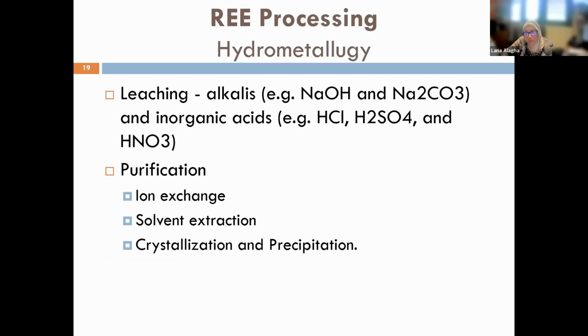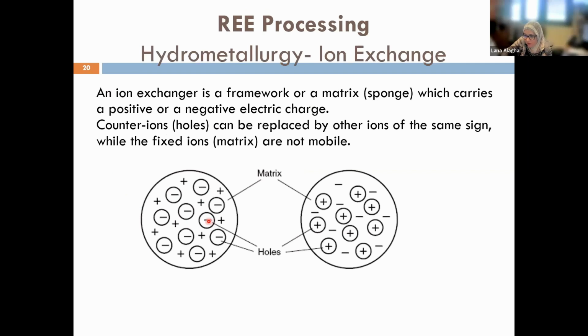Hydrometallurgy of rare earth, which is a chemical dissolution. We discussed physical separation to produce a concentrate that has mainly rare earth oxide. Now the hydrometallurgy part of the processing involves leaching and solution purification in order eventually to have pure rare earth compounds. So the agents for leaching involve alkalis like sodium hydroxide or sodium carbonate, or the use of inorganic acids like hydrochloric acid, sulfuric acid, and nitric acid, while for purification, these are the commonly used methods in rare earth processing: ion exchange, crystallization, precipitation and solvent extraction. If you are not that familiar, ion exchange is usually a resin.